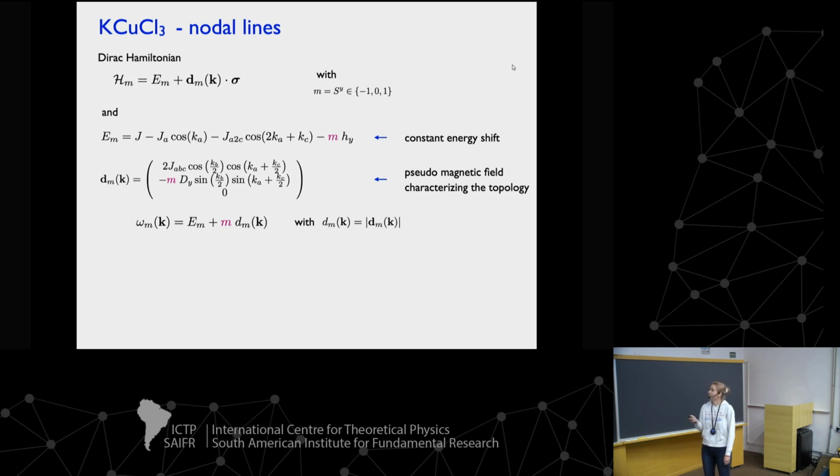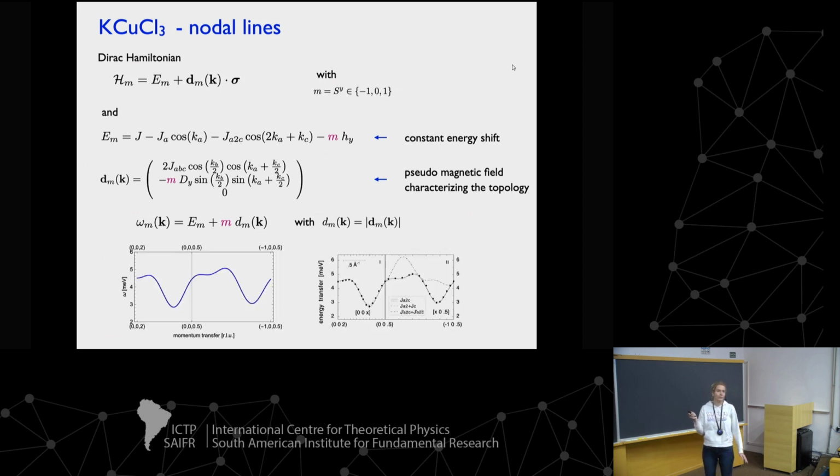Right. So if we just use the parameters previously determined from fitting the neutron spectrum, we can calculate the band structure with this simple Hamiltonian, and it looks pretty similar to what has been measured. So this is a good effective Hamiltonian for the triplets, although it's very, very simple compared to what we would need if we wanted to do the full triplet wave or bond wave analysis.